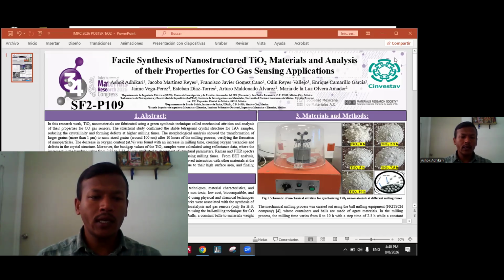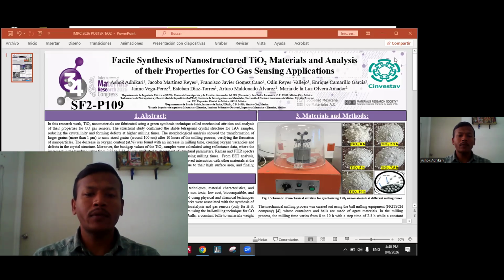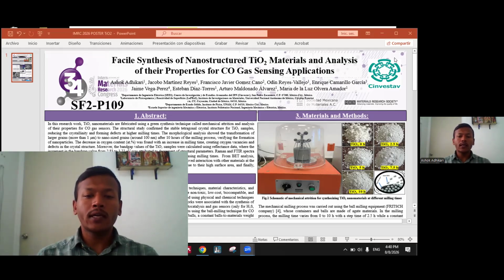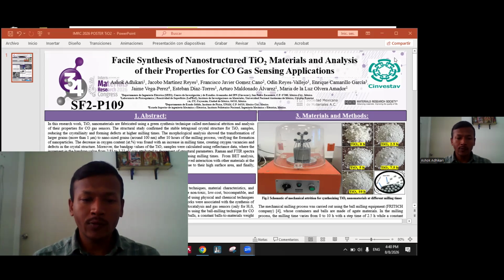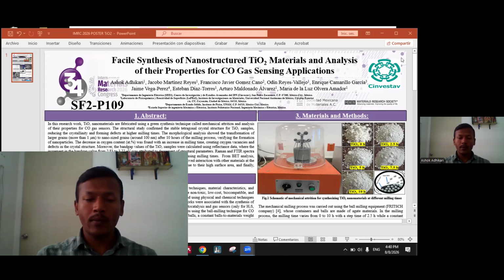From BET analysis, greater surface area and pore volume were found for milled samples, which leads to improved interaction with other materials at the molecular level. Nano-sized TiO2 samples allow more interaction with the target gas due to their high surface area, and finally improve the CO gas sensing response for milled TiO2 samples.